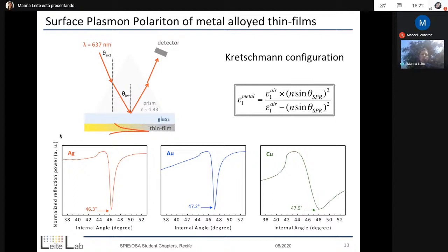And what you can see here in these examples in the bottom graphs, where I'm showing you silver, gold, and copper, is essentially the reflected power as a function of internal angle. So as we rotate the angle, this external angle here, we can actually capture an angle that is going to show very, very low reflection. The reason why I get a very low reflection in our detector is because at this particular critical angle, we are then exciting our plasmons, okay?